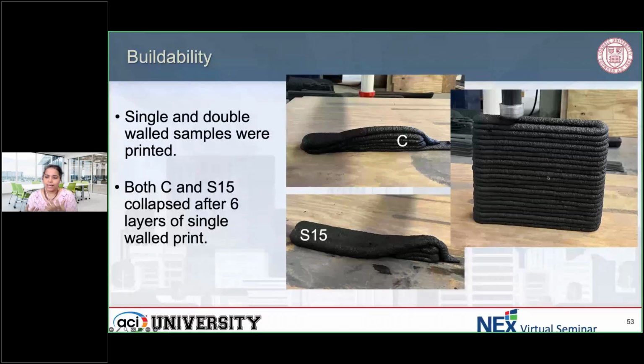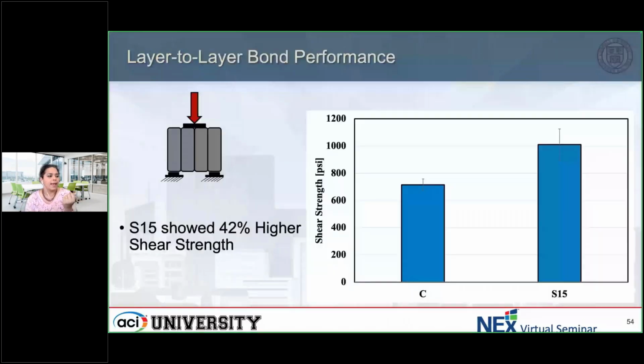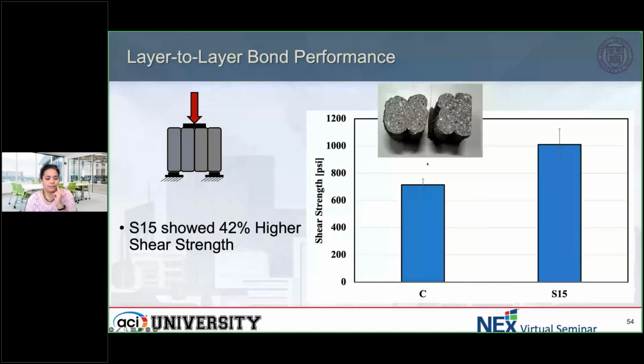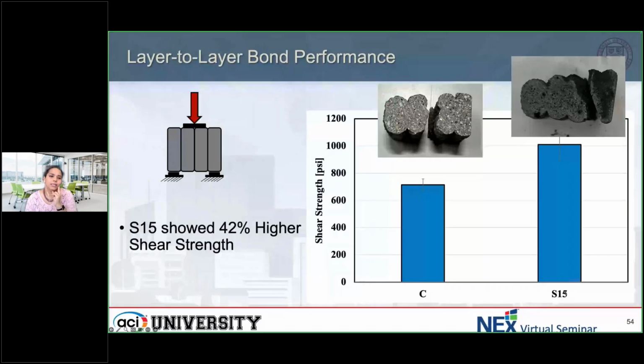So all this to say, there is a lot that goes into developing a material that's actually printable. This takes a lot of hours to get to this point. So what we did was, like I said, we printed a bunch of layers and then we cut them such that we have a specific coupon size, and then we tested them to measure the bond strength. So the control failed right here at the bond, and then for the SPR 15 mix, where you have 15% of SPR, you could see it didn't fail at the bond, but it failed in the system, and it actually had a higher shear strength than the control over here. You can see there's some aggregates in the mixture as well.